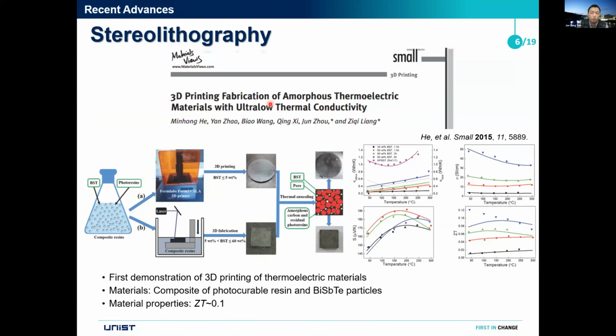This is the first demonstration of the 3D printing of thermoelectric material based on bismuth antimony telluride-based material, which is a workhorse thermoelectric material operable at room temperature. In this paper, the authors used a stereolithographic 3D printing process based on an ink composite of photocurable resin mixed with bismuth antimony telluride particles. After making some 3D shaped objects, these objects were thermally annealed at very high temperature. Despite high temperature annealing, these final products still have some organic residue, which significantly degrades the thermoelectric property. So the ZT value was at the time just 0.1, which is just 10% of the ingot property.